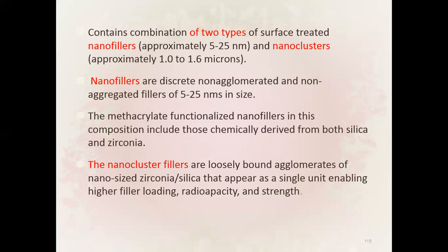Nano fillers are discrete, non-agglomerated, and non-aggregated fillers of 5 to 25 nanometers in size. The methacrylate functionalized nano fillers in this composition include those chemically derived from both silica and zirconia. The nano clusters are loosely bound agglomerates of nano-sized zirconia or silica that appear as a single unit, enabling higher filler loading, radio opacity, and strength.